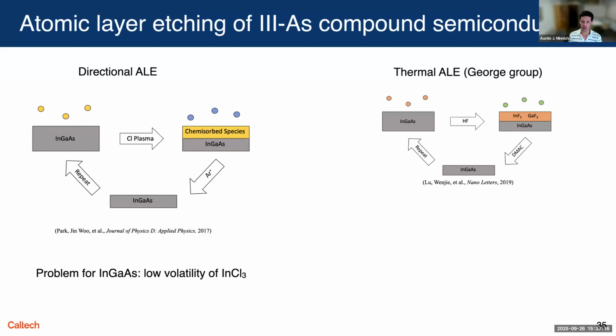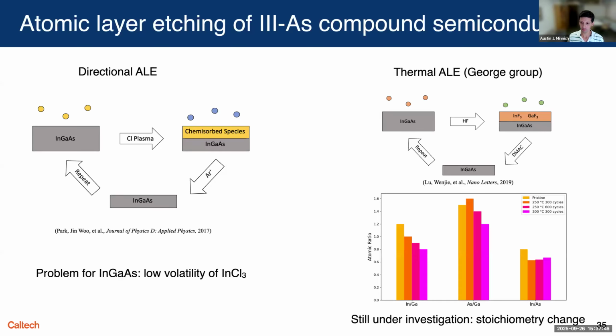Recently, there's been a lot of interesting developments in what's known as thermal atomic layer etching. And that's where you don't use any plasmas. You just expose the surface to various gases or precursors, and that also can etch. So one really interesting work is where they exposed InGaAs to HF, which produced those fluorides that you see. You can then use a precursor dimethyl aluminum chloride, or DMAC, which was found to produce etching. And that's a great process. There's still indications that it changes the stoichiometry, which is a little bit of a complicated plot, but the main takeaway is that the stoichiometry changes as the process goes, which may be okay, but it also may not.